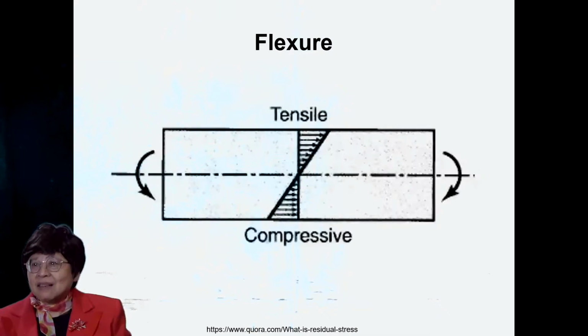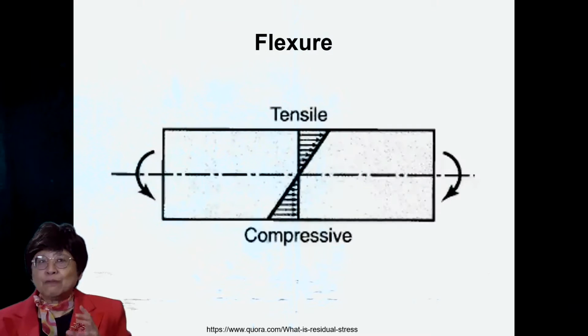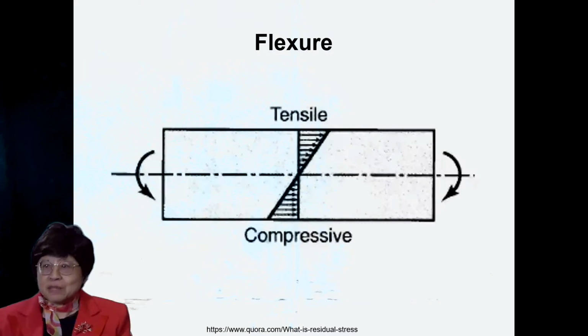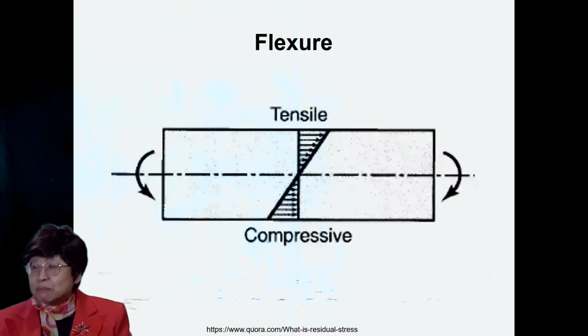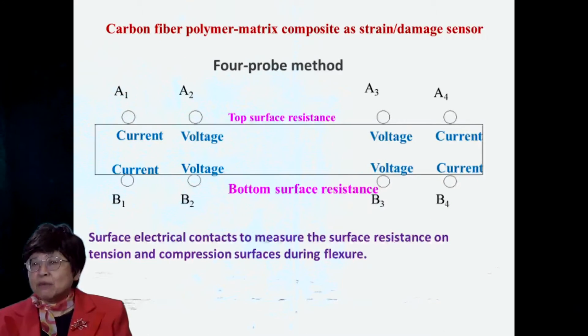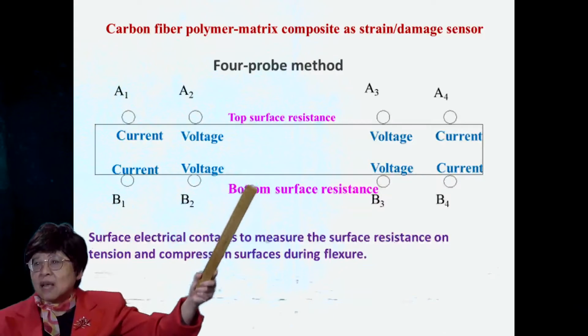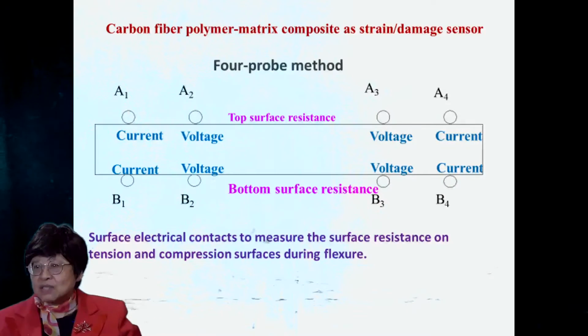In spite of that, the surface resistance is very suitable for tracking the flexure. Because under flexure, the tension side and compression side, the two opposite sides, are feeling opposite stresses. One is tension and one is compression. And one can put 4 electrical contacts on each of the two opposite surfaces to measure the top surface resistance and the bottom surface resistance.